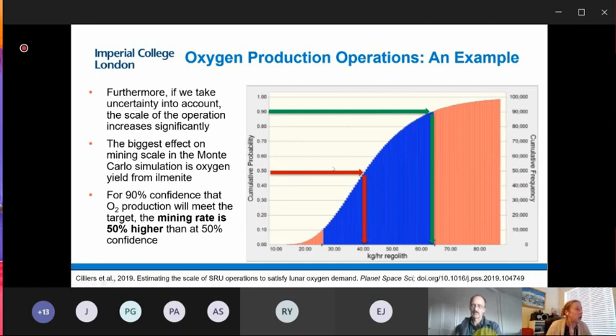And we carried out Monte Carlo simulations that showed that if we have a 50% confidence rate, our mean mining rate is just over 40 kilos an hour to produce 1,000 kilos per year of oxygen. But if we want 90% confidence of producing that rate, then the mining rate goes up to over 60 kilos per hour. And if we are reliant on that oxygen supply on the surface of the moon for survival, then I think perhaps maybe 90 to 95% confidence would be more reassuring than 50%.